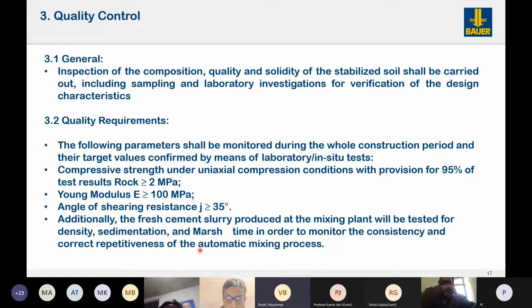Usually we are able to achieve compressive strengths up to 2 MPa to almost 4 MPa and modulus of roundabout 100 MPa to 200 to 300 MPa also. And we are also able to increase the angle of shearing resistance up to 35 degrees, which is a very significantly high value when we are trying to improve soft soils.